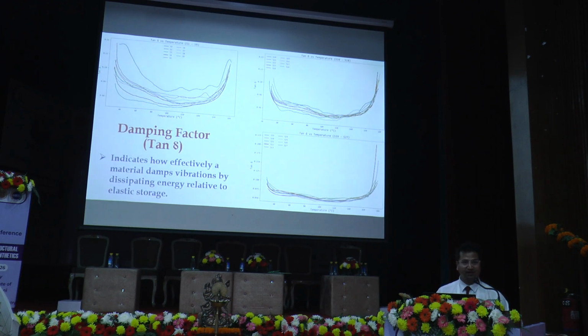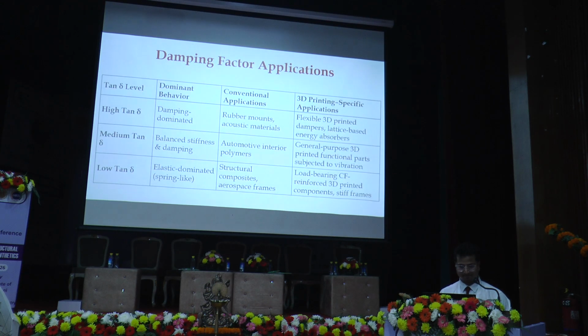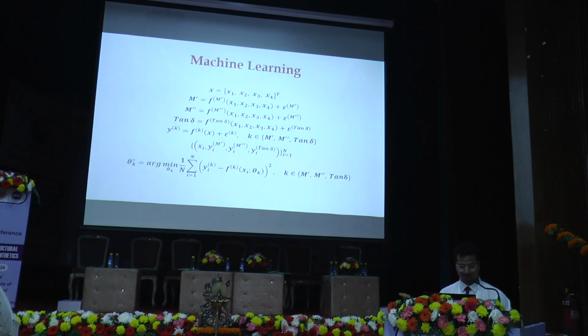Damping factor. The damping factor is the ratio of loss modulus to the storage modulus, and it indicates how effectively a material damps vibrations by dissipating energy relative to elastic storage. These are the damping factor applications. In 3D printing specifically, there are 3D printed dampers and lattice-based energy absorbers as well. General purpose 3D printed functional parts, load bearing carbon fiber reinforced 3D printed components, and stiff frames.